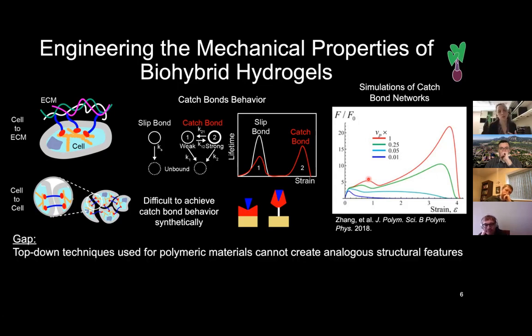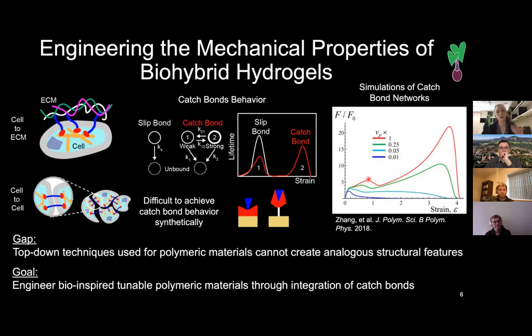So really, it's been difficult to create these top-down techniques using polymeric materials, though there's been some work to achieve these. But right now, a lot of the molecules get created as single, small molecules, and when they looked at them under sonication, where they stretched them, they only broke at the linker between the chain and that small molecule that should give you these catch bond behaviors. So why not try to create these synthetically? We're going to try and use biology to create these catch bonds since they already exist in these systems. So really, can we make these tunable polymeric hydrogel systems by integrating these biological catch bonds?